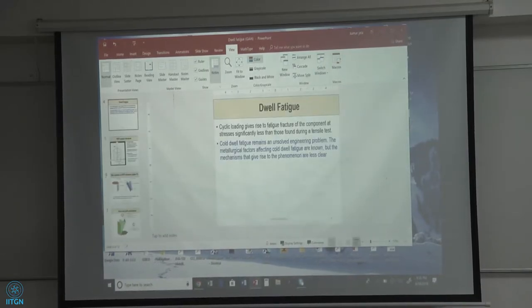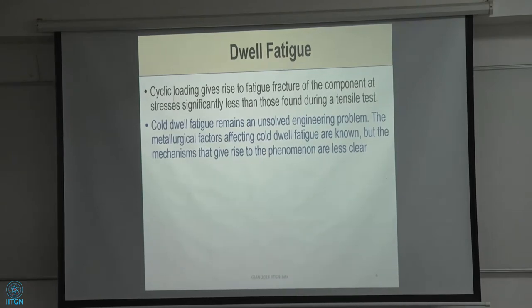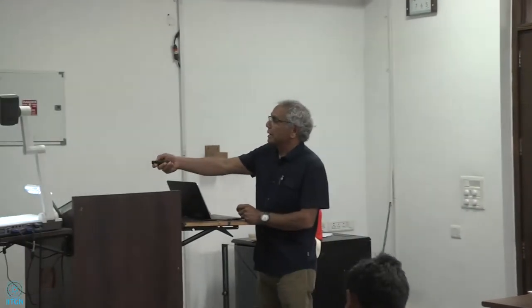So this cold dwell fatigue is cold in the sense that in titanium alloys, it can take place around 120 degrees Celsius. 120 degrees is pretty cold temperature for a turbine engine. It's relatively cold, right? And it's a 40-year-old problem. It was first observed in some titanium alloy disks, not the turbine disks, but fan disks, in the Rolls-Royce RB211 engines, I don't know exactly what they are, the Lockheed TriStar aircraft, okay?